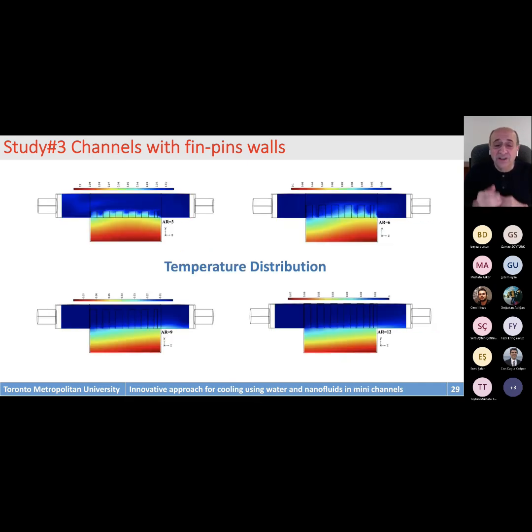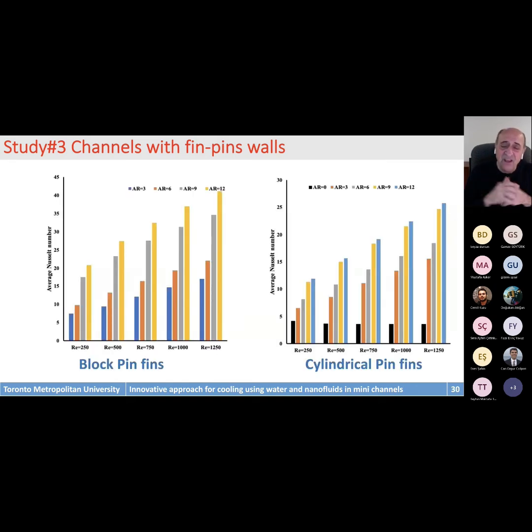And when it comes to the temperature, this is very obvious. You can see in the top one, for instance, we have a sharp temperature gradient coming from the heated block and then shooting up to the pin fin, and the mixing extracts more heat in this particular one. So this attracted our curiosity, and this is the reason why in one of the experimental studies, we are varying the height of the channel and the height of the pin fin.